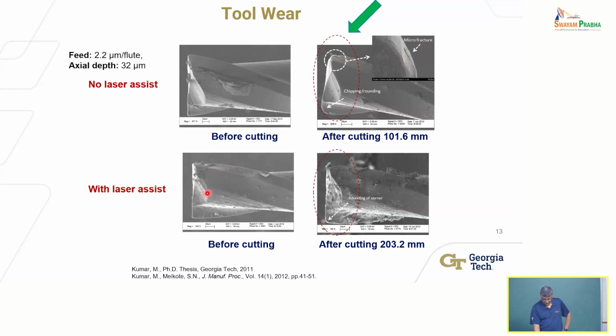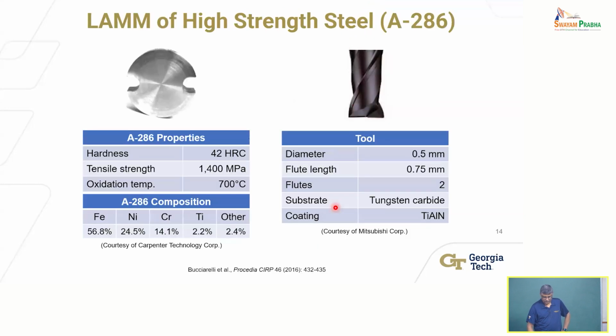With laser assist, you see some material adhering, certainly, because now the tool is seeing softer material, so it's going to stick. That built-up edge can be a problem. But you can see that the shape of the tool isn't bad. There is some edge rounding. Now this is cutting twice as long as the previous tool, 200 millimeters, and still it's not too bad, but there is material adhering, okay? That ideally should be removed. It shouldn't happen. You have to somehow get around it, and there are ways to get around it. Without going into further detail, we can talk about it towards the end. There are ways to be investigated, that through lubrication or other methods, you can actually minimize that, okay? All right.